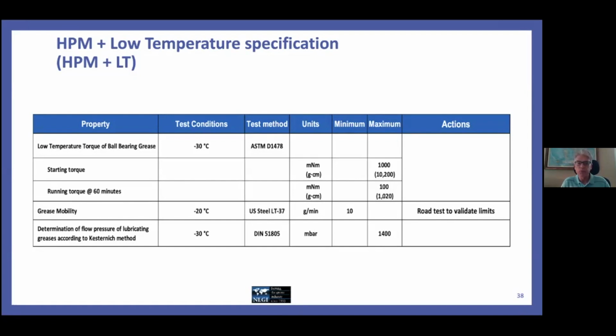And again, due to a scarcity of data that we were able to lay our hands on, we include this in the requirement for some road testing to validate to make sure 10 is the right minimum at -20C. And -20C was chosen to be cold, but not frigid, not Arctic. There are issues trying to run that test at too low of a temperature, apparently.